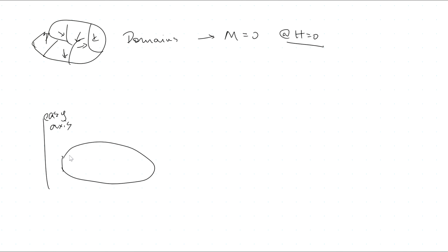So effectively, our magnetic moments within domains would prefer to be aligned vertically, and it would break into domains, but in this case, all domains align along the easy axis. So if you're able to visualize magnetic domains in your magnetic material, then you would see something like a striped structure, a striped domain structure.